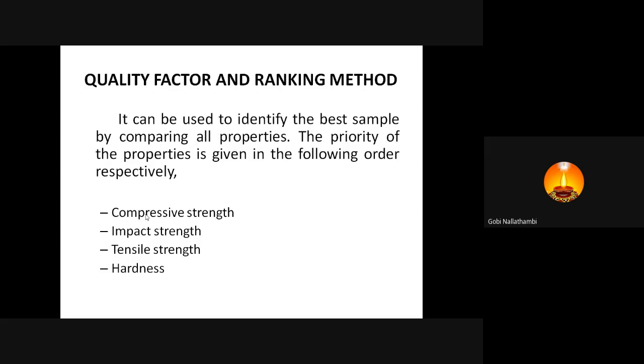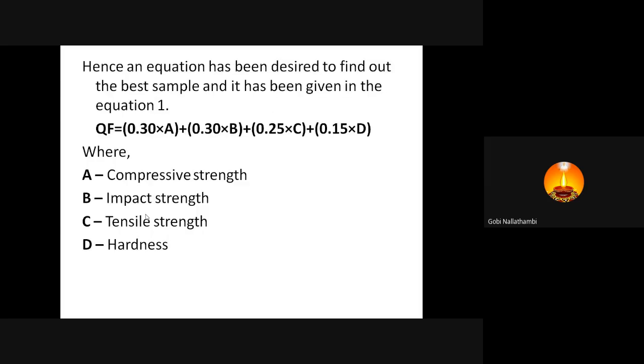To identify the best sample, we have to give weightage to the four measured properties: compressive strength, impact, tensile, and hardness. So this is the equation to obtain the quality factor. Here A is compressive strength, B is impact strength, C is tensile strength, and the hardness weightage is 0.15.